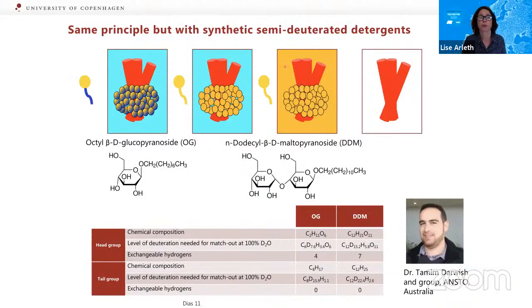In parallel to this, we pursued the same principle, but with synthetic semi-deuterated detergents instead. We could see that even though we really loved the nanodisc approach, we also lost a lot of good membrane proteins on that account, because the whole sample preparation is sometimes challenging with the nanodiscs. So we thought that if we go back and work with invisible detergents instead, then that would ease our life.